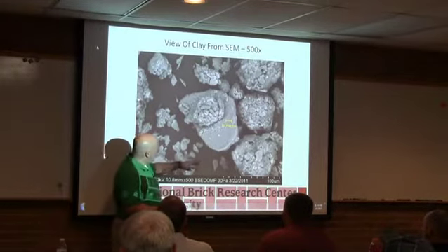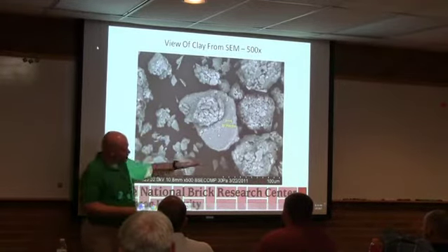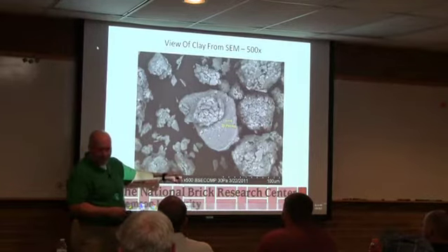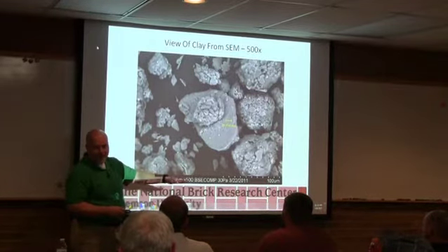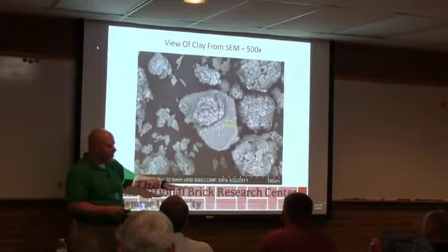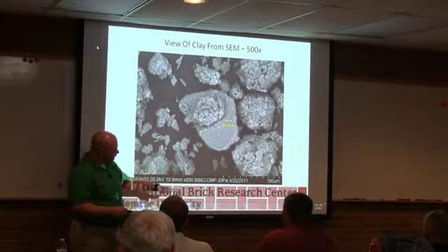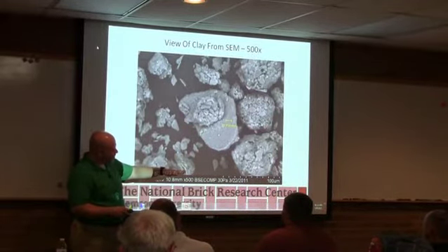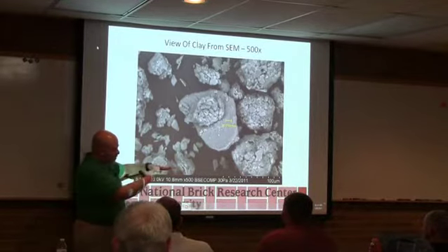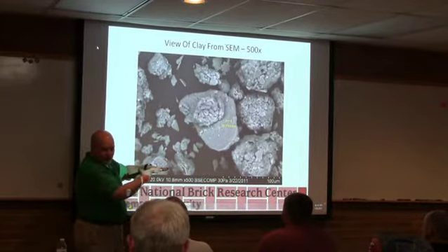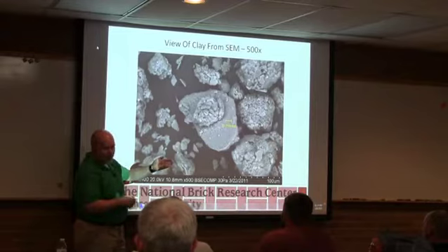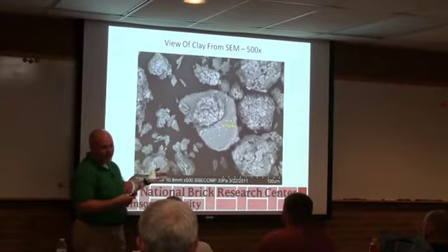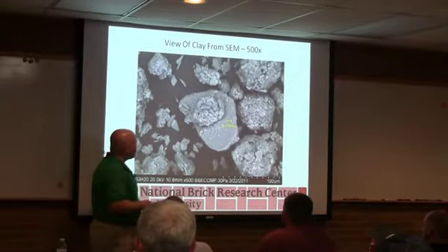So the sedimentation assumes you've got a sphere settling at a certain rate. Well, you really have a plate. Okay, so it doesn't settle at the rate you're expecting it to. In the laser scattering, sometimes you've got a particle lined up like this for the laser, okay, and it's scattering off that. Sometimes it's sitting on edge and it scatters differently. So you get different results based on particle shape.